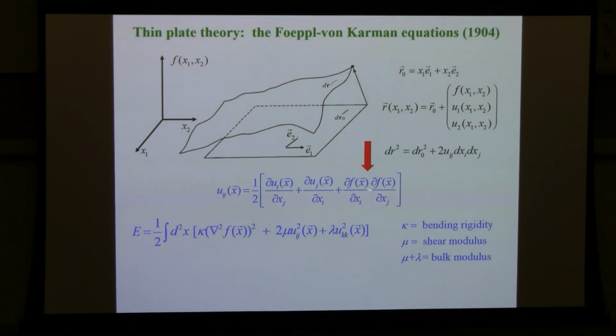But it's a nonlinear thing that shifts the gradients of the phonons, and it comes in terms of this tensor, in terms of these two terms, mu and lambda, these elastic constants, which themselves go back to the 19th century. And then there's this other interesting term here, this bending energy that comes in as the Laplacian of F squared. So there's a very soft restoring force to these flexural phonons, somewhat stronger force due to this term here, which is the stretching energy, and it involves rotationally invariant contractions of this nonlinear 2x2 matrix. And so notice they talk to each other because the F appears inside the Uij.